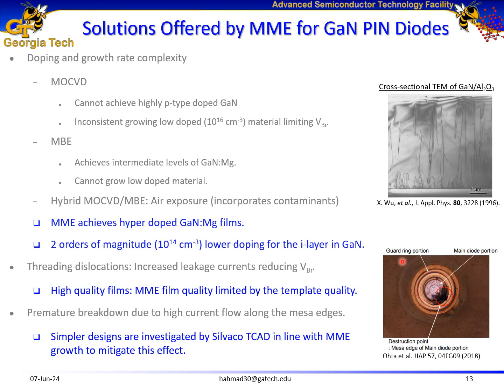I talked about the challenges in gallium nitride pin diodes, and in this slide I'm going to talk about some of the solutions that MME offers for those challenges. The first solution is that MME achieves hyper p-type doped gallium nitride films, and I'm going to show later that we have achieved 2 orders of magnitude lower doping for the i-layer in pin diodes. Also, in another study I'm going to show that we have achieved high quality films which are limited by the template quality, not by the regrown film quality. And I have investigated simpler designs by Silvaco TCAD in line with MME to mitigate the high current along the mesa edges issue.